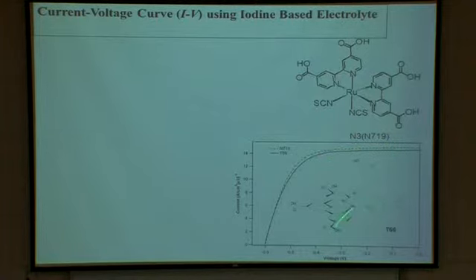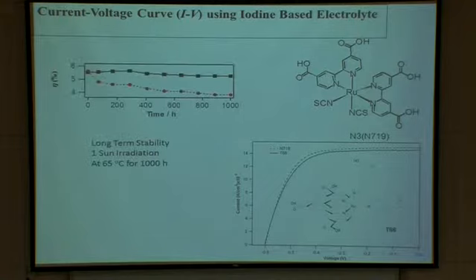As you see, the T66 gave similar currents to N719, and the same fill factor and voltage. We did not beat it, but the long-term stability was much higher. The red one is for N719, the black one is for the T66. These are real solar cells that we shine with light, one sun, for 1,000 hours, approximately 42 days, at 65 degrees, and we measure the efficiency every couple of days.